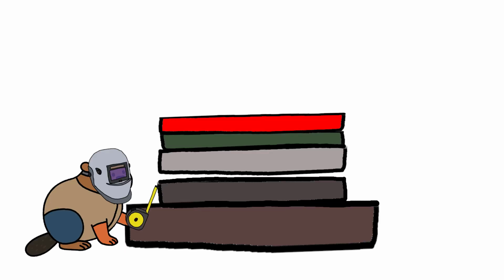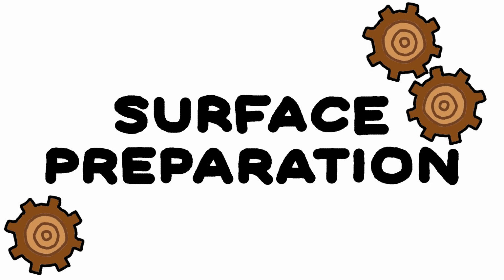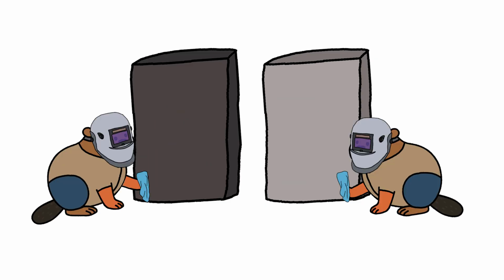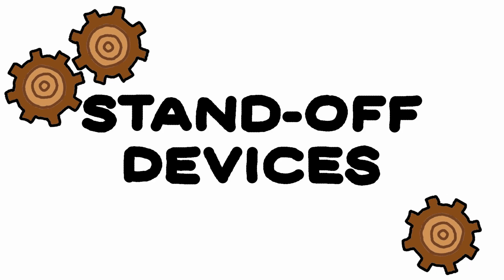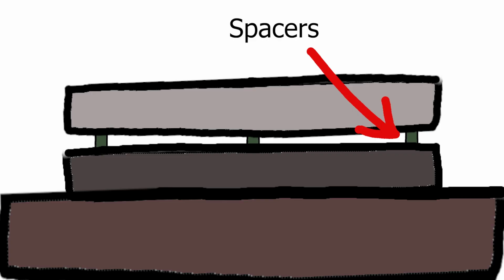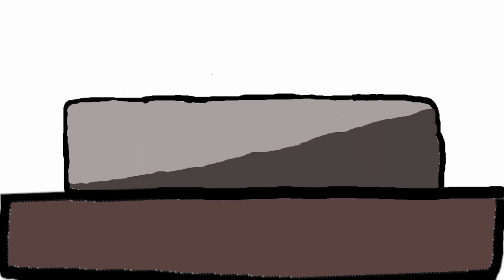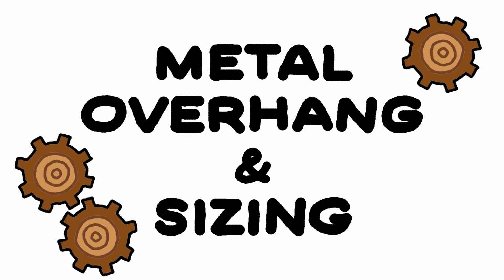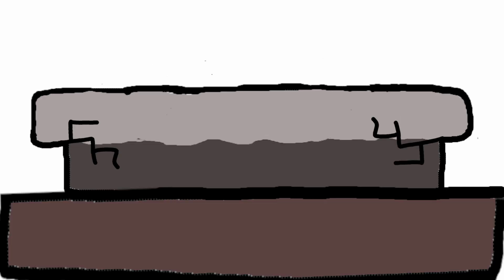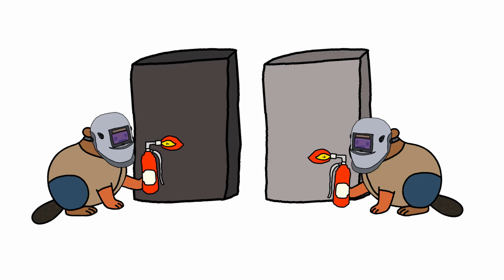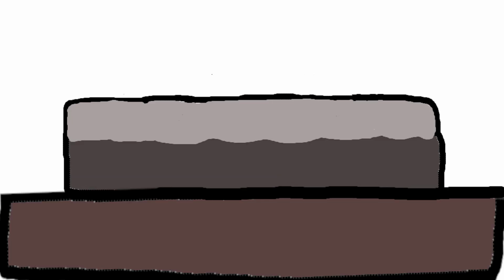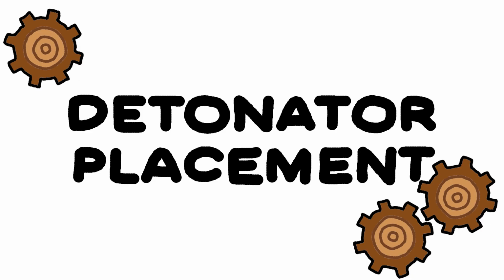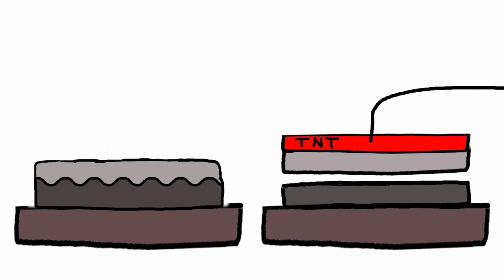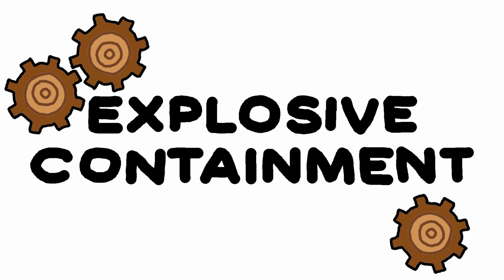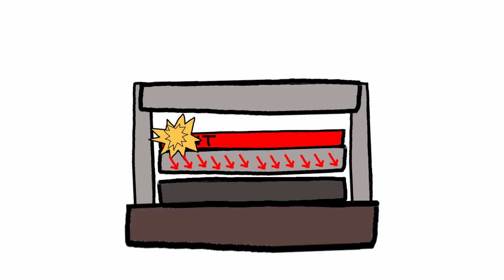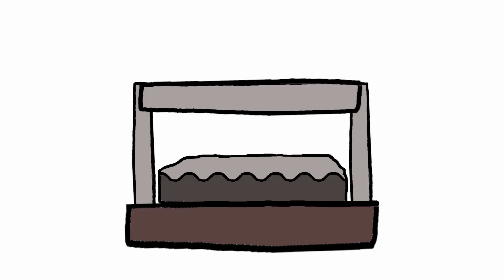Other variables that fine-tune the process include surface preparation, removes oxides and dirt so the metals fuse without contaminants; standoff devices, holds a consistent gap, preventing soft spots or uneven bonding; metal overhang and sizing, extra bonded area at the edges, reducing weak spots; preheating, lowers residual stresses and helps dissimilar metals bond without cracking; detonator placement, keeps the wavefront smooth, avoiding gaps or overlaps; explosive containment, directs the blast energy, improving wave formation and reducing edge defects.